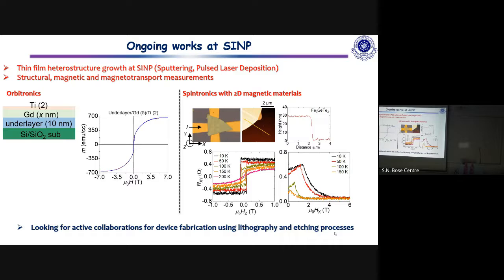And it was not only shown by us, but also other people as well. We basically then showed that you can also use a magnetotransport way to get the signatures of the existence of these textures. So once we exfoliated these materials and made devices out of it, these are roughly 30 nanometers in the size of the flakes.